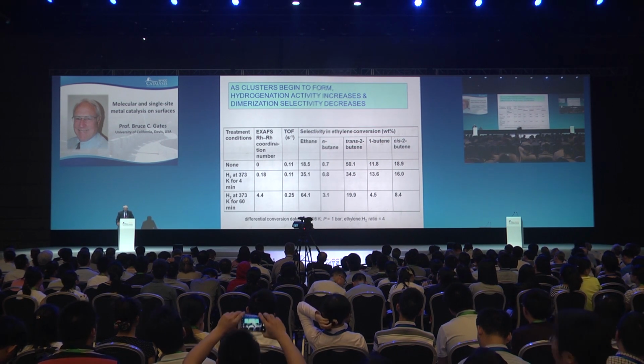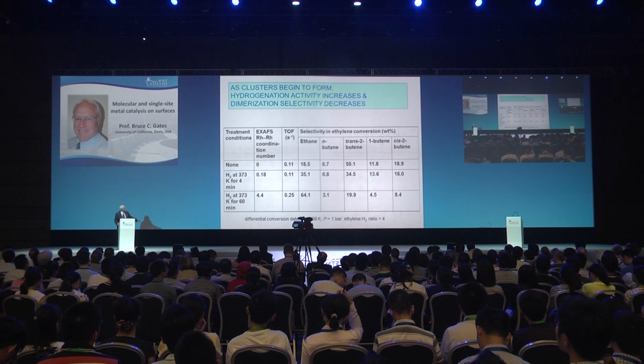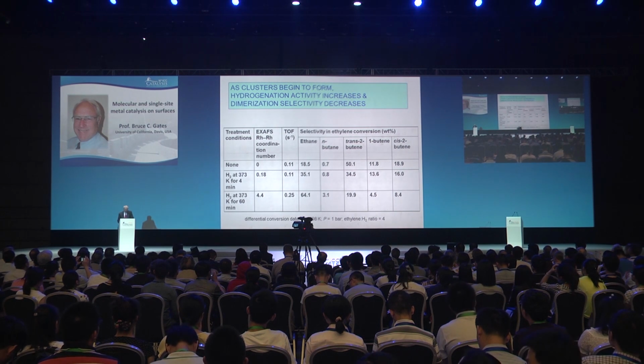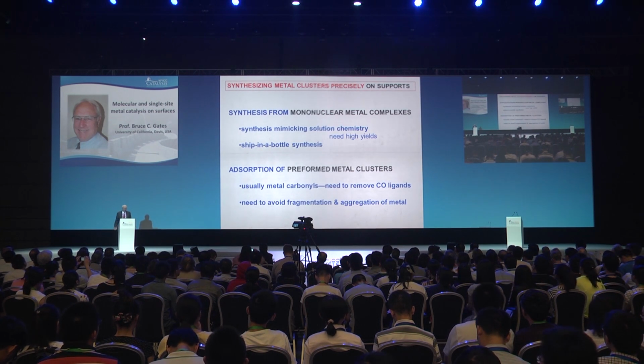Neighboring rhodium centers facilitate activation of the hydrogen, and correspondingly the selectivity for alkenes - the dimers - is going down. So we're tuning the activity and selectivity by changing the nuclearity of the supported catalyst.